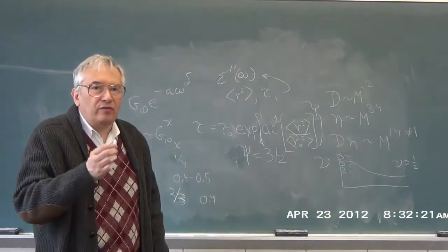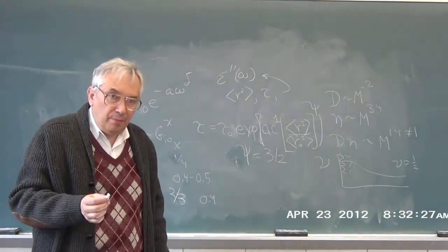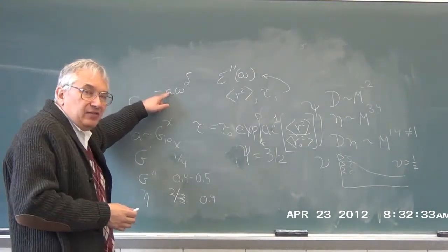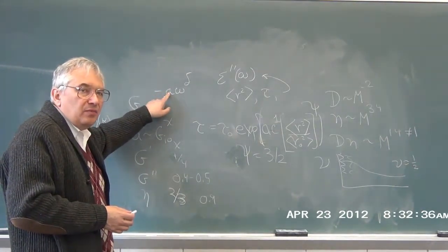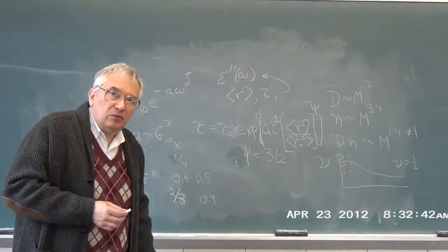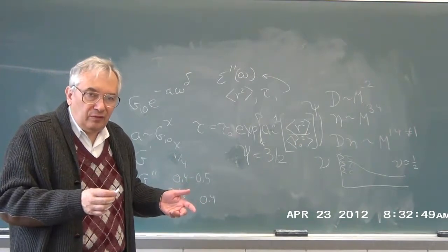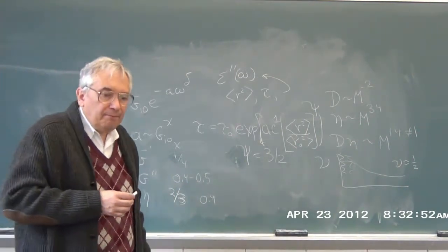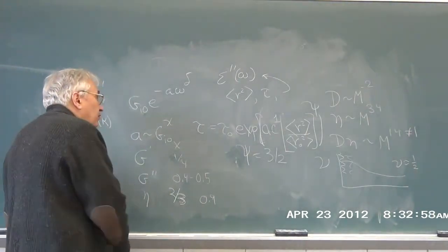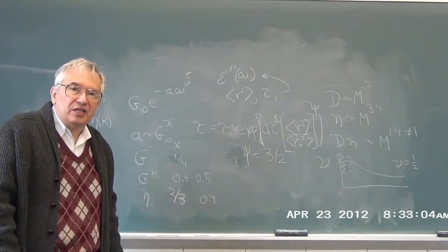However, if you look at the graph, for each chemical system, the correlation for shear thinning is superb. And therefore, this object, which is basically a dynamic parameter in some sense, is being entirely determined by what in some sense are the low frequency properties, which are pseudostatic properties. Okay. So you can relate dynamic parameters to static parameters and actually see interesting things.